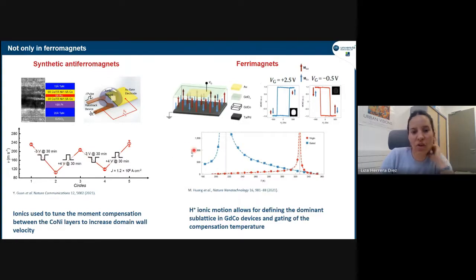So when you measure the coercive field of the system as a function of the temperature, there's a divergence of the coercive field at the compensation point. And then, as I explained before, the compensation point can be moved around with a gate. So if they record this as a function of the gate voltage, they could really see that this compensation temperature could be moved around with the gate.